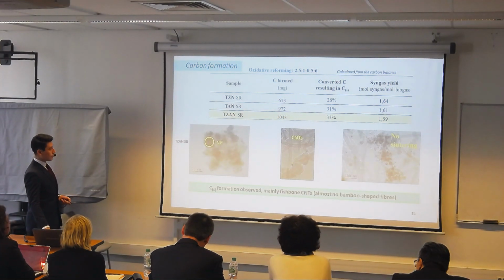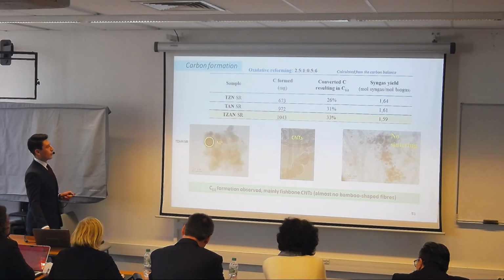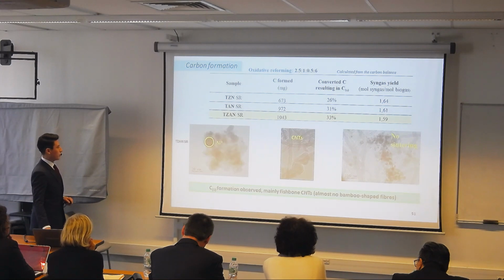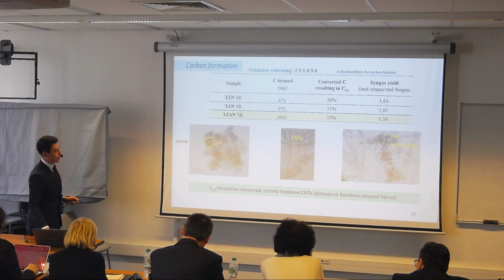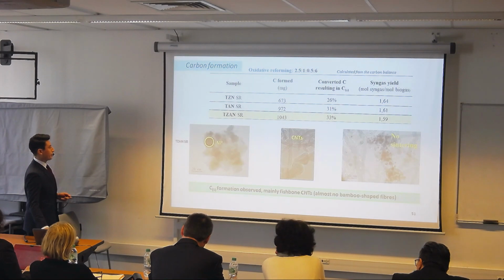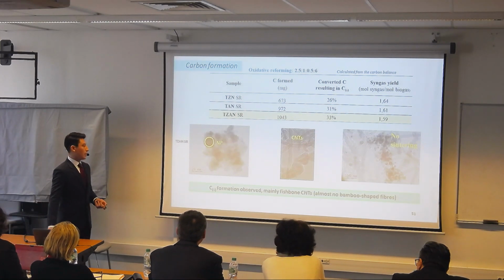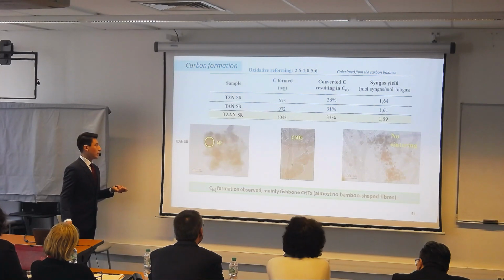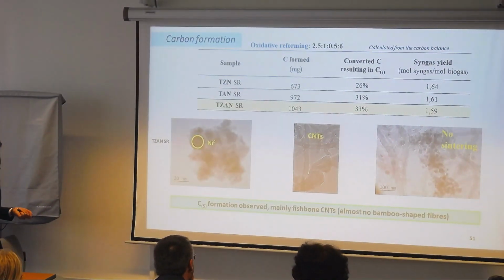synthesis. We also find that the best catalyst had the higher carbon formation, and as I was mentioning, there is no sintering, or there is no proof of that. And in this case, the main kind of carbon nanotubes corresponds to the fishbone type. And about the bamboo shape, there was no evidence in the TEM characterization.